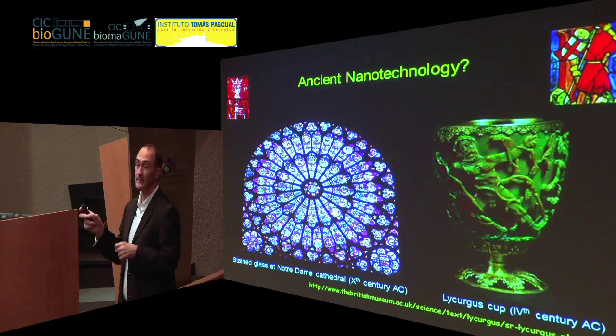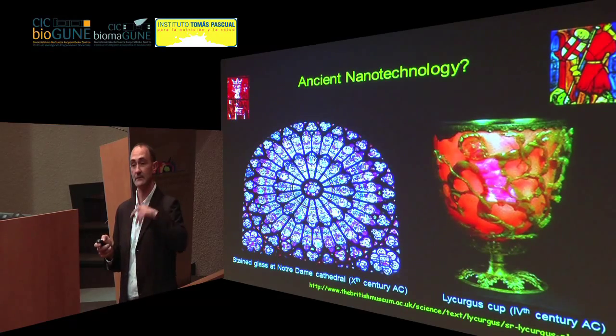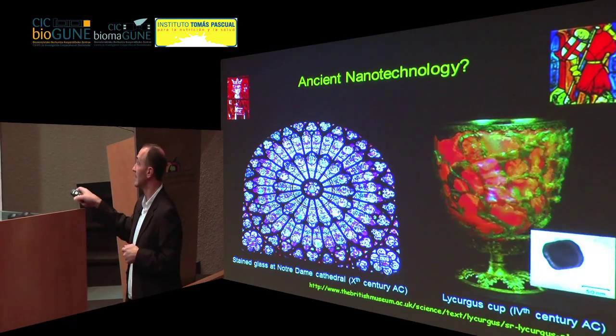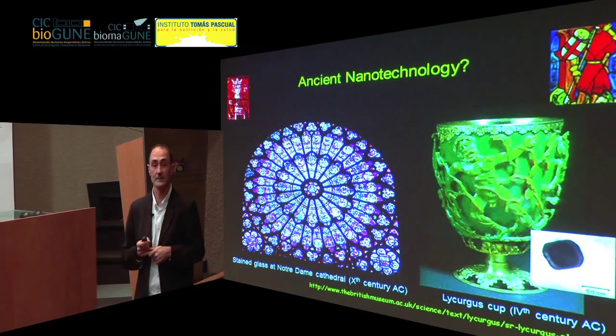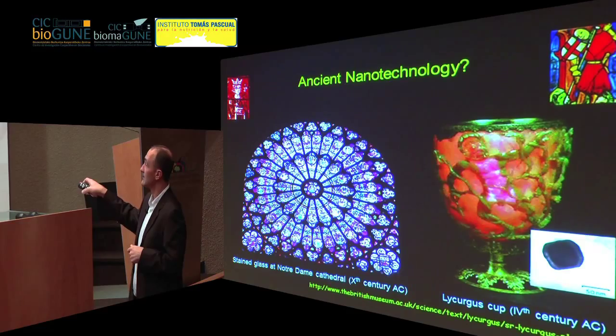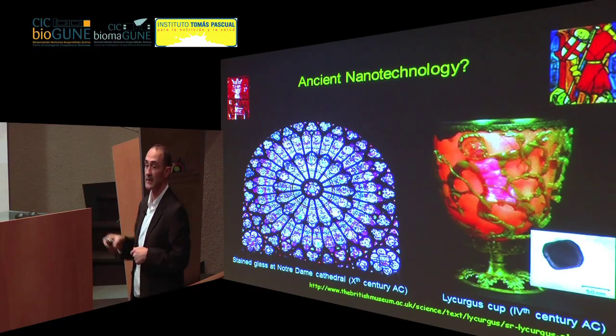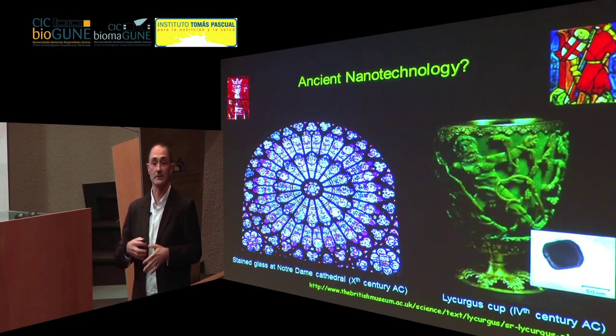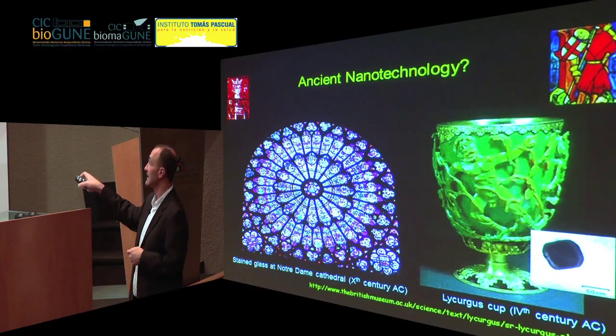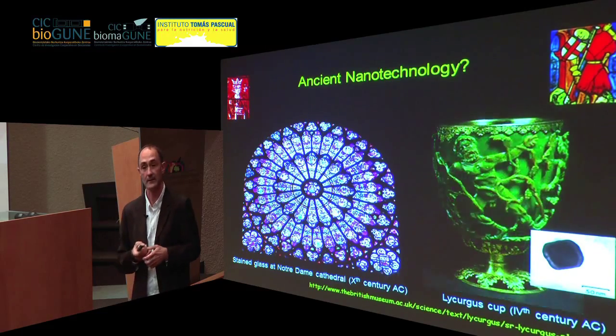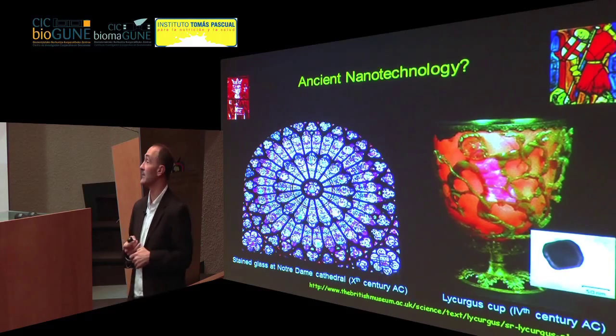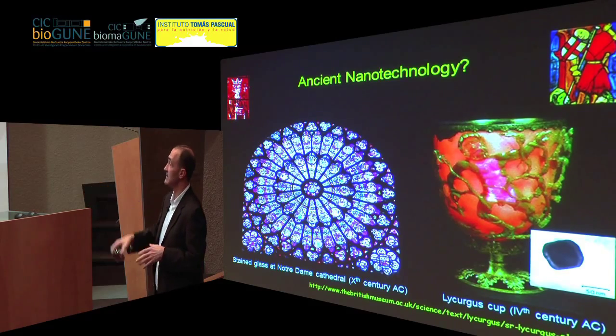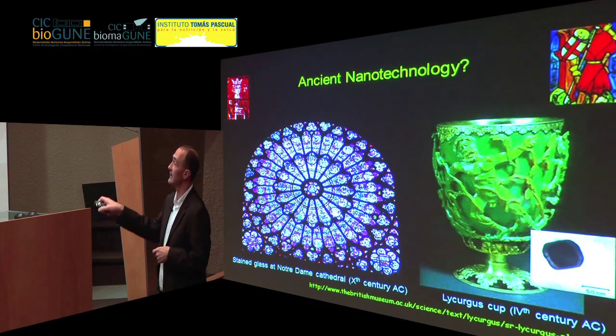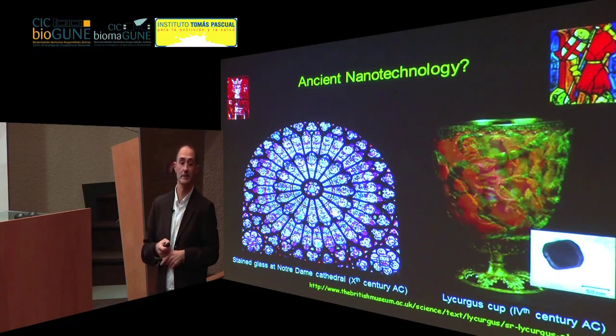If you take a little piece of the glass and put it on one of these grids and take it to the electron microscope, you find many of these tiny particles, which are made of gold and silver. So it's the composition, the morphology, the size, and the concentration of the particles that lead to this color display in this really old cup. Again, this was exploited very often in the Middle Ages for making, for example, stained glass in old churches.